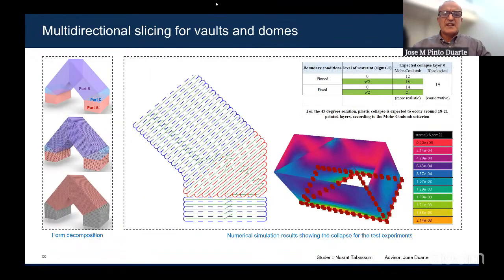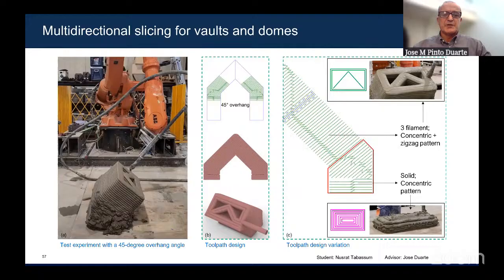In this case, we are just using horizontal and diagonal slicing, and trying to understand how to move from one to the other and see if the part is printable. You can see the part. It looks like it collapsed, but it did not collapse. It's being printed this way. There's a lot of over extrusion on the bottom part, but this was a successful test in this case.